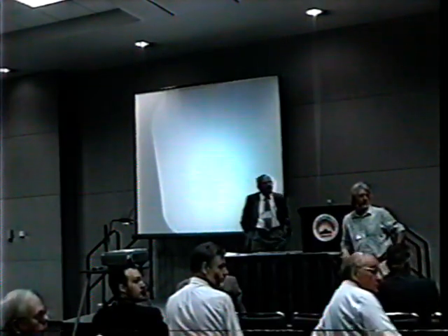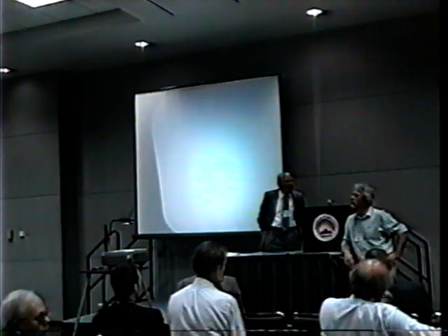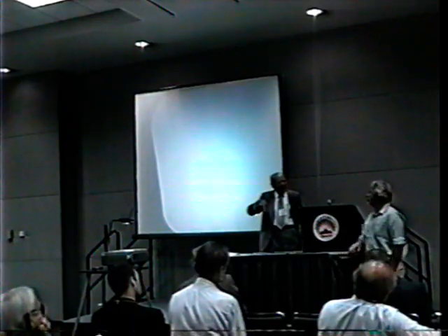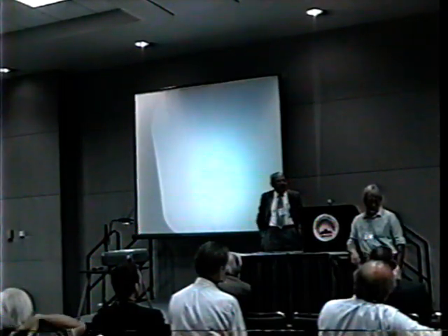Since you mentioned film adherence, do you have a lot of problems with the films blowing off, blistering? Do the films, once they're plated on, tend to blister off as they're loaded? Yes, well, that depends how you prepare it. If you prepare it so there is a rather extended dendritic type, then of course during the gas evolution you will have some loosening, the production of some loose particles in the electrolyte.